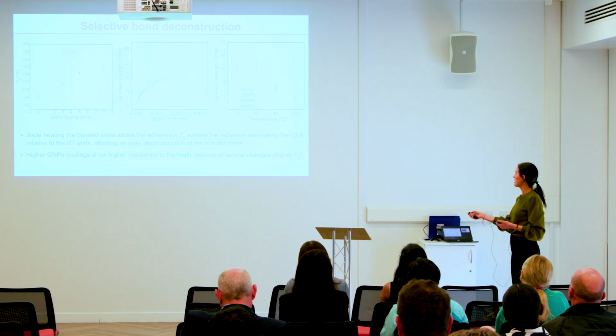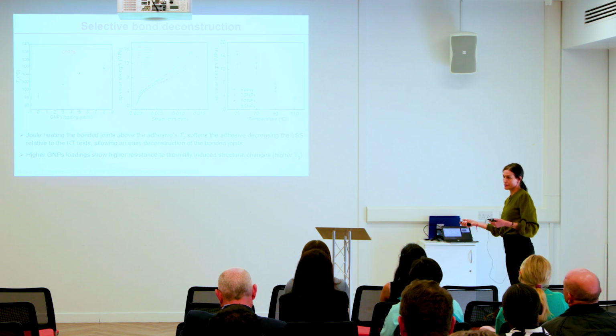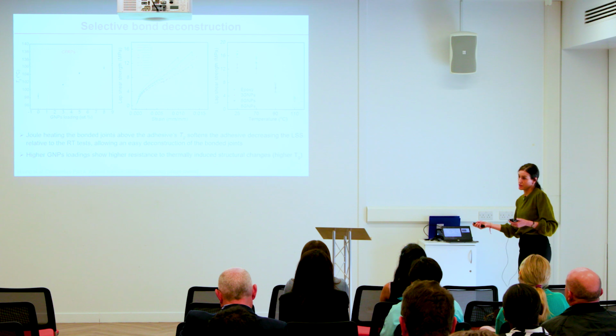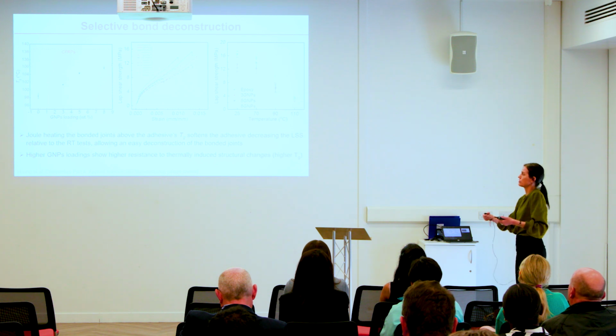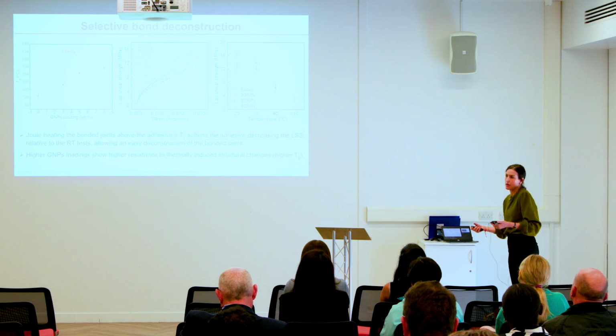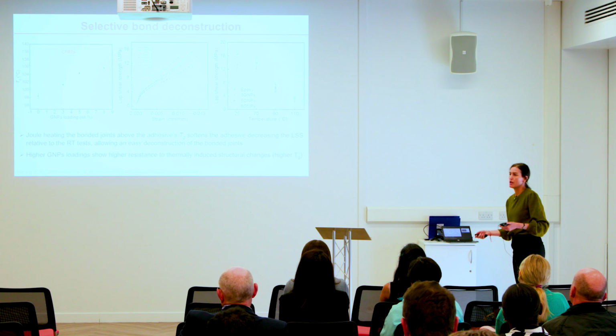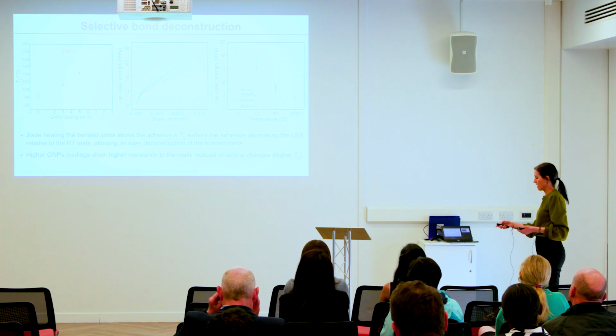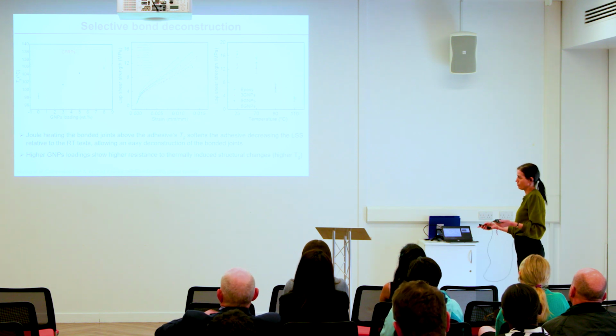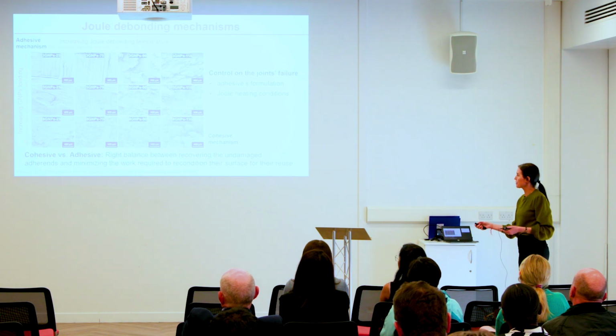And in particular, when we are above the Tg of the adhesive, we can see that the lap shear strength is particularly low. It's very, very low, which means that the deconstruction is very easy and we don't need to apply a lot of energy and we are not damaging the structural properties of the composite.